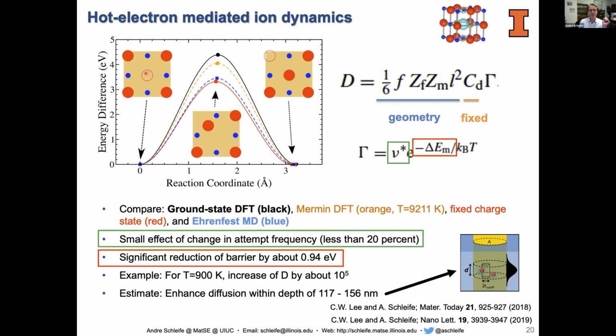And we use this transition state theory approach here, where the defect diffuses from this position here over to the corner of the cell, which is actually symmetry equivalent to the starting point, but anyway. And then we look at how large is this barrier in the ground state. Ground state is maybe 4.5 electron volt or 4.3. And then how much does this barrier change if the defect is excited?